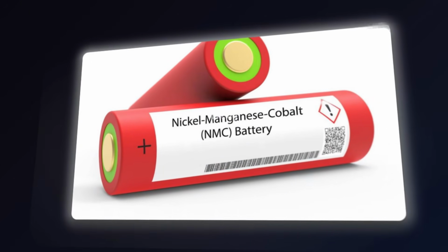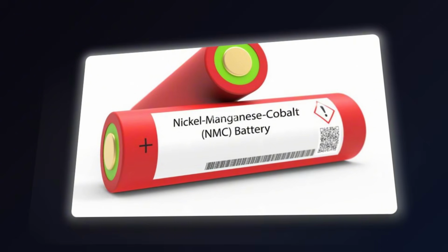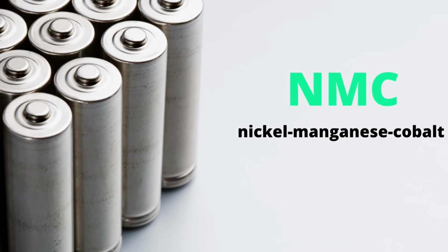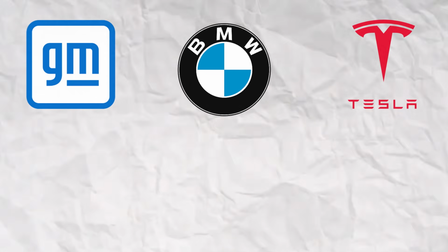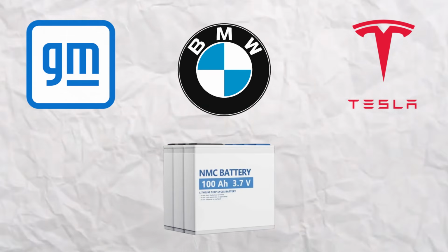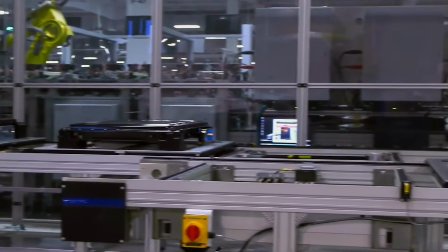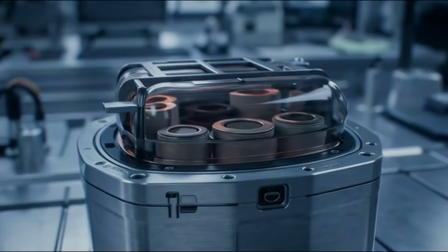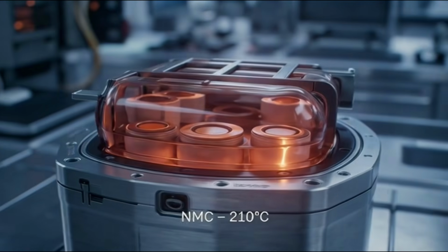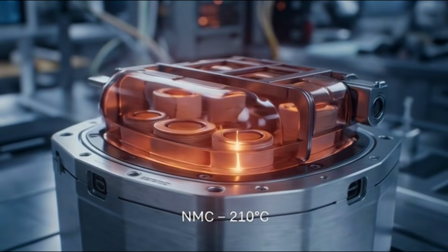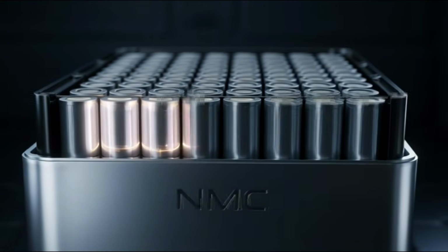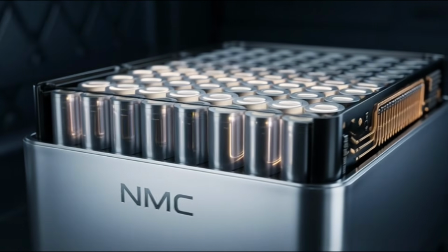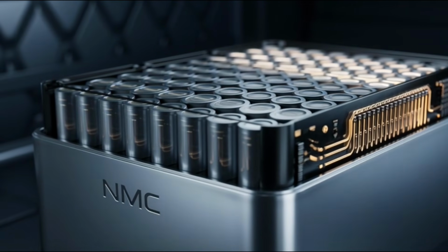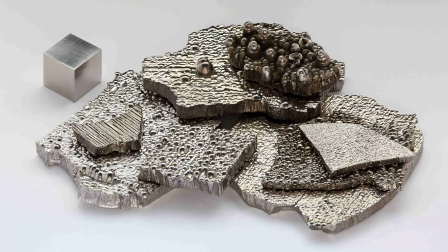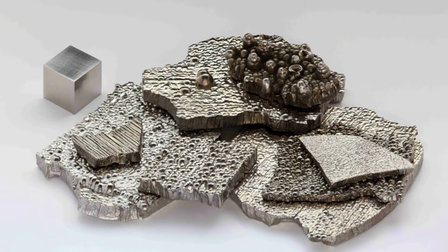Second, NMC, nickel manganese cobalt oxide. This is the evolution. Automakers like GM, BMW, and the current Tesla long-range vehicles use NMC. It's a little more stable than NCA, a little longer lasting, and it hits thermal runaway at around 210 degrees Celsius, a meaningful improvement. The energy density is still fantastic, range is excellent, performance is great, but it still has cobalt in it. And cobalt is expensive.